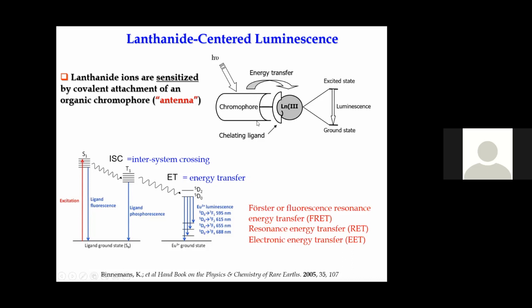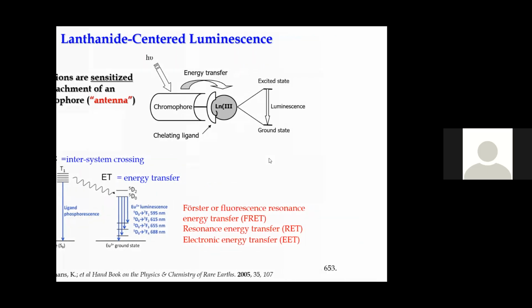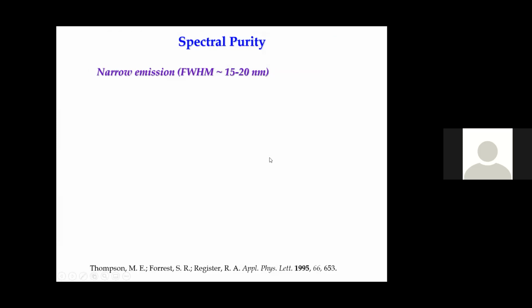So what we want to do is make a nanoparticle and coat it with the ligand so that we can shine light on the ligand, it absorbs light, it gets transferred to the metal center, and the metal gives light off. Believe it or not, nobody has done this with a nanomaterial before us. That is fascinating. So we wanted to give it a try and see whether it works with lanthanides. Other features of lanthanides are that their emissions are very narrow. You see the full width at half maximum is about 15 to 20 nanometers.